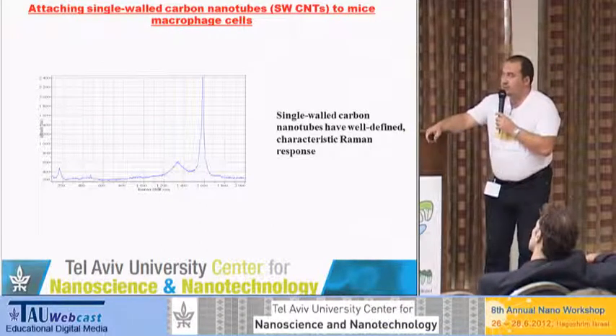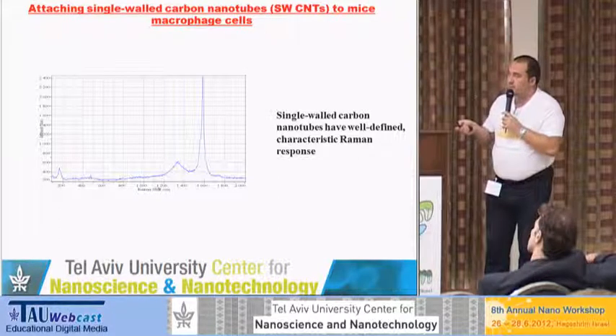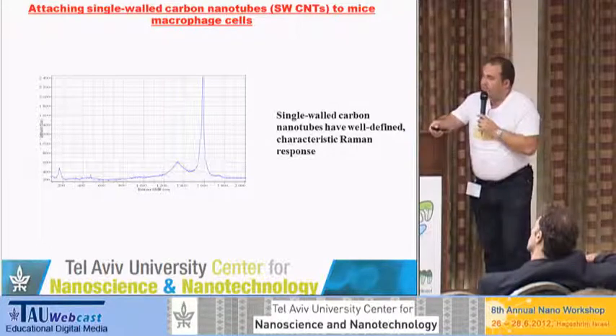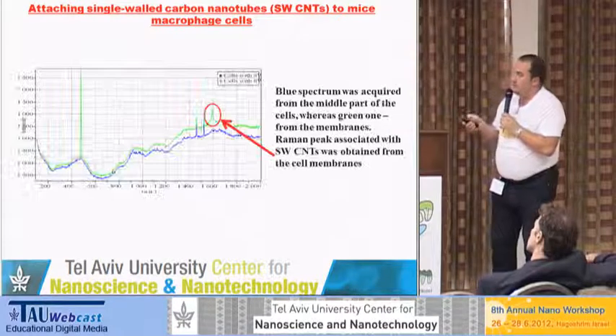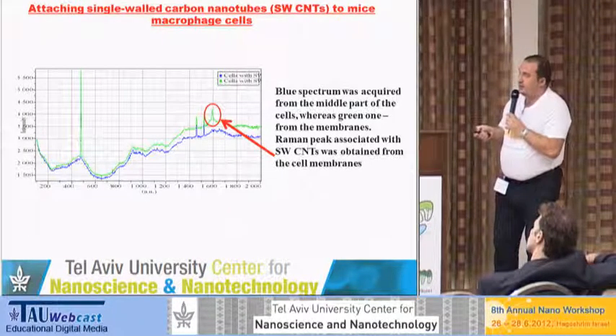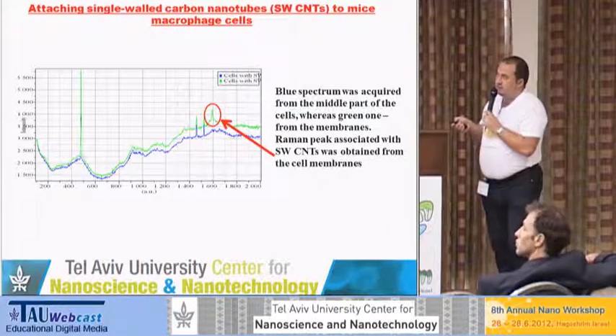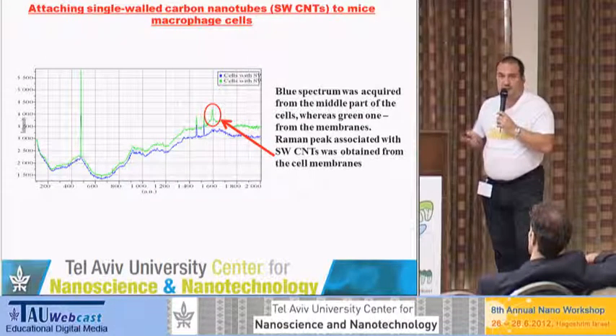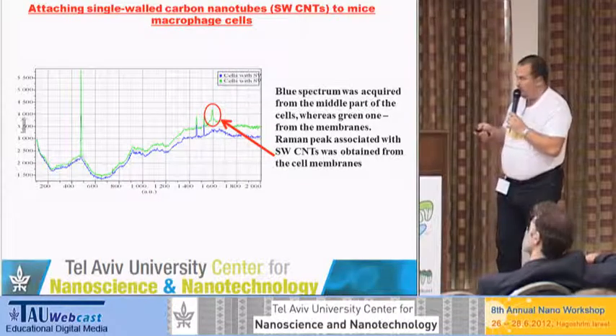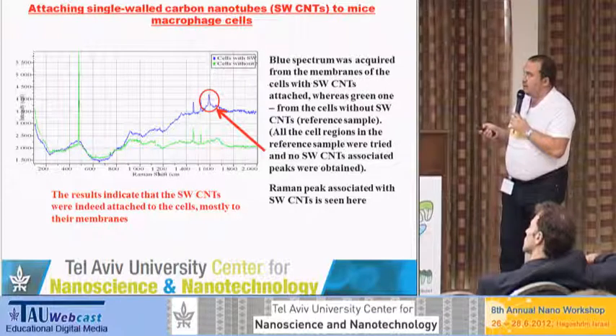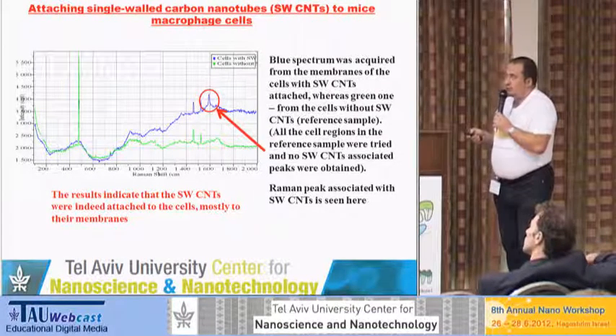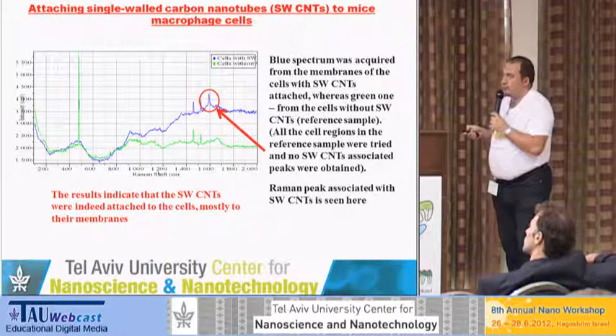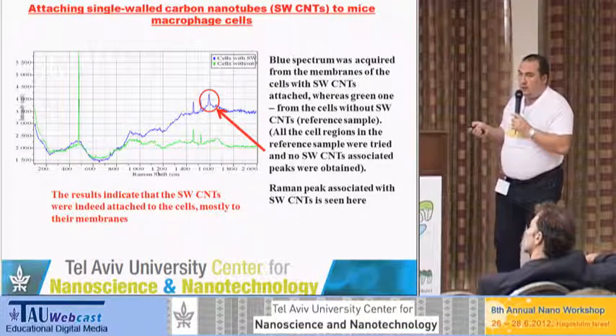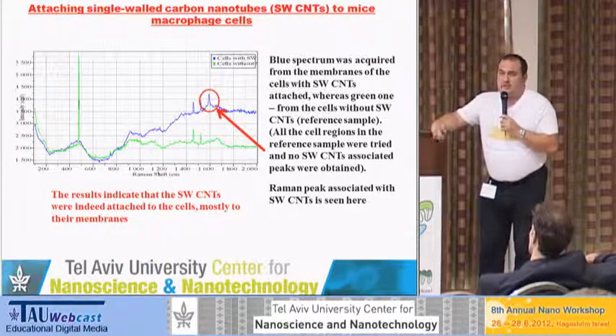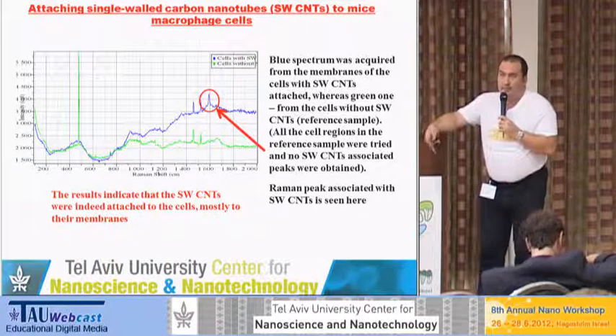As you know, carbon nanotubes have a very well-defined peak at slightly less than 1,600 centimeter minus 1. And for example, on this spectrum, you see the spectrum obtained from the membranes of these cells and from the interior of these cells. They're quite similar, except that on the membranes we see a characteristic peak exactly on the position where the single-walled carbon nanotubes peak would appear. We also took control cells where there was no functionalization with carbon nanotubes, and we can see that on the control group this peak doesn't appear. So we can conclude from this that indeed the functionalization of cells with the carbon nanotubes succeeded and that they are primarily attached to the membranes.